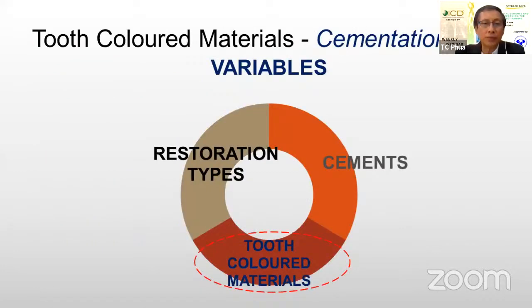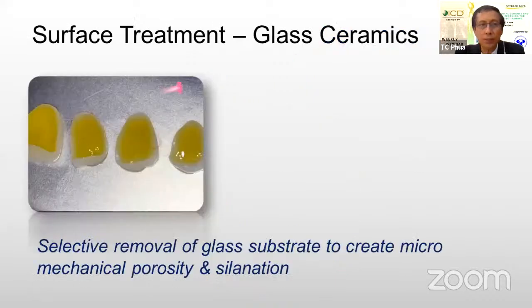The other variable relates to tooth colored material. And here we have a revision of what I have said earlier, and I'll finish this lecture, in that if you're treating glass ceramic, we can selectively etch it, not with phosphoric acid, but with hydrofluoric acid. And the attempt over here is to create microporosity or retention for us to insert a silane type material to improve upon the wettability of this material.